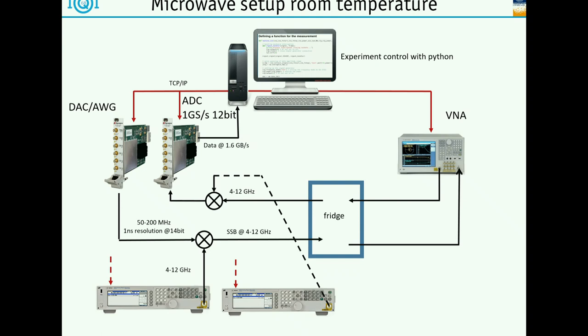The best way to do that is, again, mix them down from these couple gigahertz to something like 10, 20, 30 megahertz, which you can then easily digitize using an analog to digital converter, which samples with, for example, a nanosecond or something like that, and that transfers the data to the PC, where you can post-process them and so forth. There are also additional instruments like this vector network analyzer, which allows us to do frequency sweeps. So, for example, measure the transmission spectrum of a resonator very efficiently.